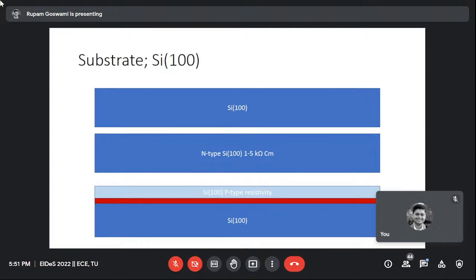If you want to start with an N-type or highly resistive substrate, then in this case we can have diffused resistors. If you want to make a diffused resistor version of the pressure sensor, we cannot use a simple silicon 100 substrate. We have to optimize what the substrate should be. That's why, in the case of a diffused resistor based MEMS pressure sensor, you have to have a highly resistive substrate 100, and it should be N-type, because otherwise your resistor will not be isolated, crosstalk will be there, and performance is directly affected.